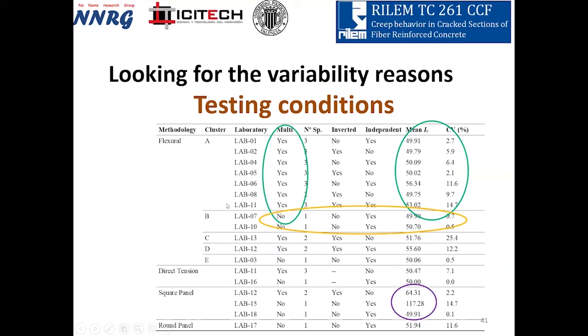It's clear that in flexural you have cluster A, which is the most supported with all the laboratories, and cluster B, which has two different aspects: working with single specimens and applying only central load, changing a little the criteria of the procedure. But only two laboratories are able to do that because they need lots of surface for the same test. For the square panel, the result was very different because each laboratory applied a different level of load, even though it was prepared to perform that.